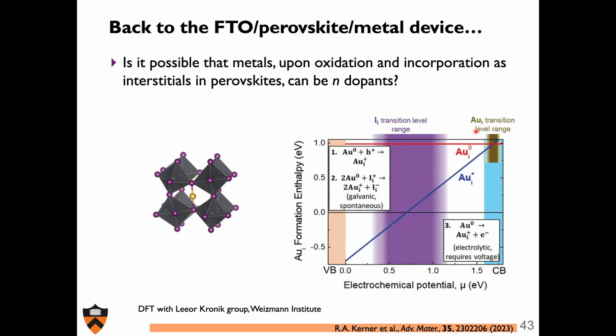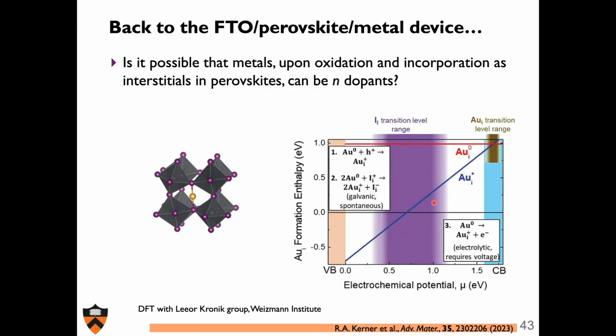And the system will also end up changing. The iodide transition will also go from minus to plus, and that'll come along for the ride as well. So you're going to change the interstitial population of iodide, but you'll also add electrons to the system. And that's basically coming along with the change of Fermi level, which will shift my interstitial population of iodide from maybe some plus, some minus to primarily minus, along with free electrons in the system. And so that's what their calculations indicated.